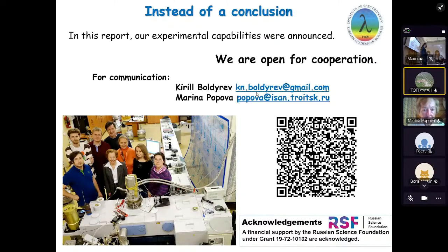Hello, Kirill. Thank you for the interesting presentation and for the fantastic opportunities that you now have in your laboratory. I usually work with semiconductor nanocrystals in solutions or in glasses, so in some dielectric matrix. In semiconductor nanocrystals there are also a lot of phase transitions, depending on the type of nanocrystal, from 2 up to 10. And the main way to see these phase transitions optically is not the luminescence spectra or absorption spectra, but luminescence excitation spectra at different temperatures. Is it possible in your laboratory to do this? Not luminescence, but excitation spectra of the luminescence.